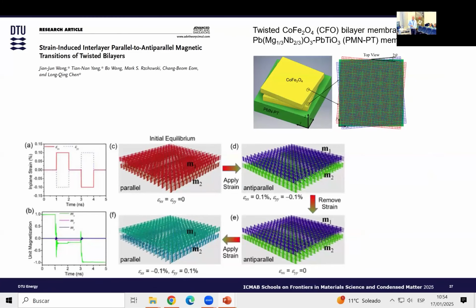Good. So there was a lot of work over the years. I would not say a lot. There were a few works over the years on twisting of oxides. This is a calculation from Longqing Chen. They took two bilayers of CFO, rotated them at a certain angle, put them on top of PMN-PT, and strained the PMN-PT. What they saw in the paper is that they could go from parallel magnetization, when they apply strain, to anti-parallel magnetization. They remove the strain, the magnetization stays anti-parallel, and then they apply the strain again and go back to the initial state. So it's basically a non-volatile way of doing this.